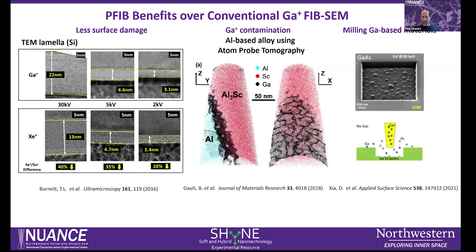Another disadvantage of using gallium FIB-SEM could arise when trying to prepare or mill gallium-based materials like gallium arsenide. In this case, you would preferentially sputter-remove the arsenic ions from the crystal structure, and you get this artifact called droplet formation of gallium that segregates in this way.